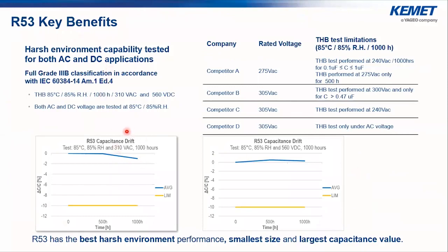Key benefits: we can see the capacitance drift on the AC test condition, so at 85 degrees, 85% relative humidity after 1000 hours. So really the capacitance drop is very stable, minus 1% after 1000 hours. And on the other side, we can see the 85 at 560 VDC rated voltage after 1000 hours, because really it's a very stable capacitance drift.